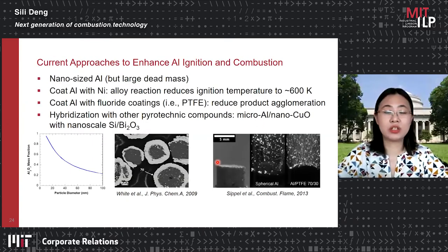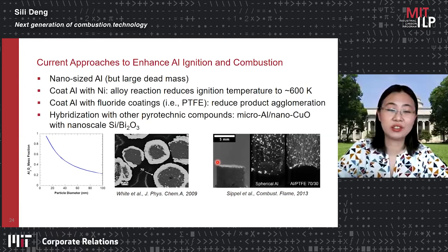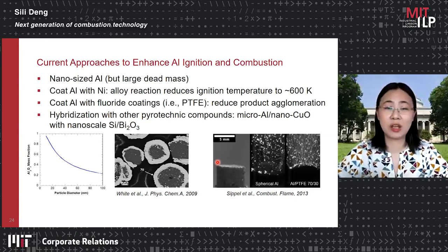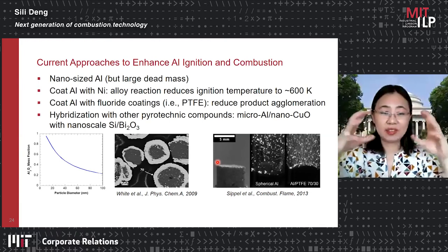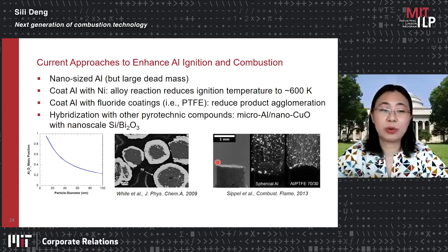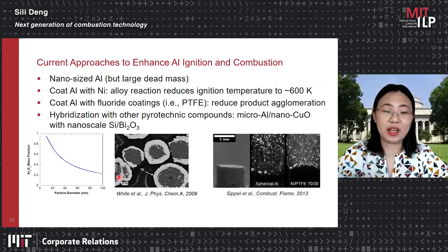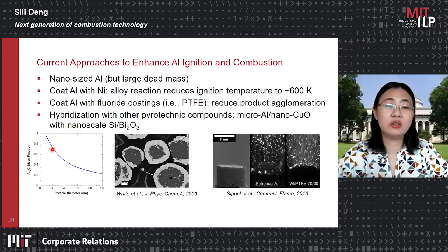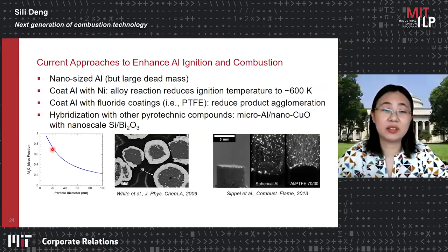And the approach, some general approach, first is to utilize nano-sized aluminum. However, we know as the size of particle shrinks, the percentage of the surface aluminum oxide becomes larger. As you can see from the diagram, if you reduce the size from 100 nanometers to roughly 20 nanometers, you see more than 70% of the mass is dead mass, which means you cannot really use them.